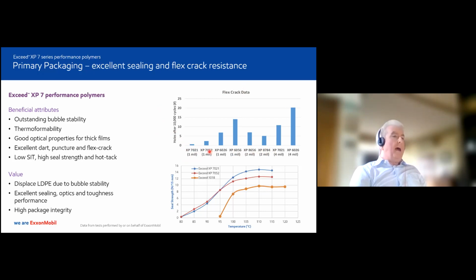Okay, and because of its really good bubble stability as well, and its incredibly high puncture resistance, it now becomes a very interesting resin to use in thermoforming applications. Okay, for thicker films, this particular series of resin does offer very good optical properties. And as you can see from the bottom right-hand corner, the sealing performance is also excellent. You can see here our Exceed 1018 series, which has been a workhorse in the marketplace for us since 1995, in fact. And it's still going strong, but if you really need that lower SIT and an improvement even on the plateau seal strength, then these grades can offer that.